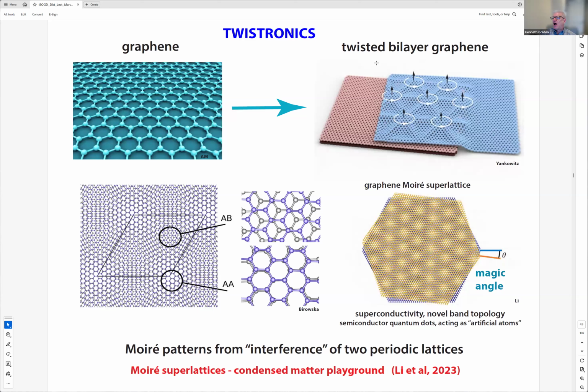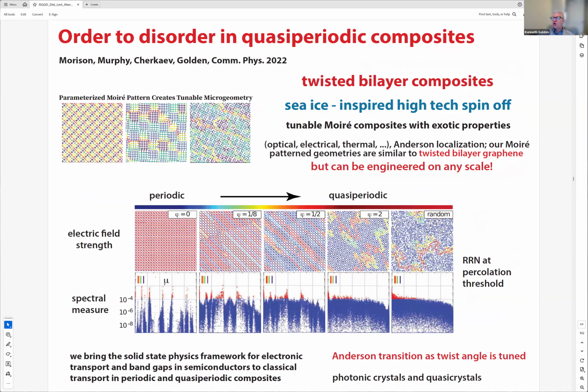And we didn't realize it at the time. It only came out in the review process that what we developed, what I call moire metamaterials, are extremely similar to twisted bilayer graphene. And so I termed what we discovered twisted bilayer composites, because it's not at the atomic scale, it's at any scale, and also it's any classical transport coefficient, not just conductivity. So we published this paper, Order to Disorder in Quasi-Periodic Composites. We should have called it a new class of materials, twisted bilayer composites. But anyway, we didn't see that at the time.